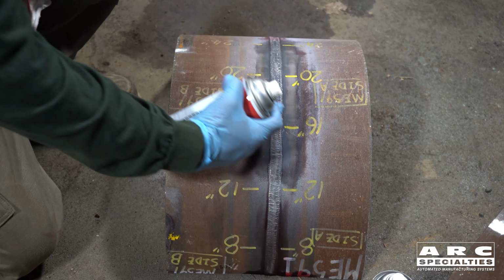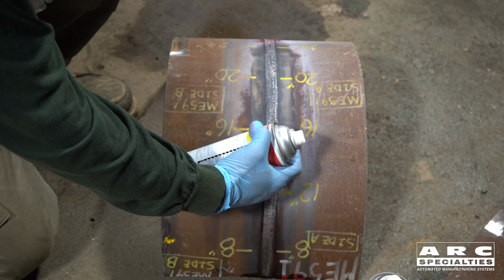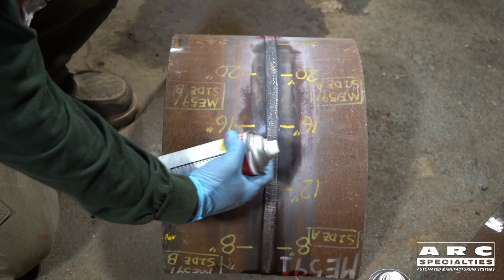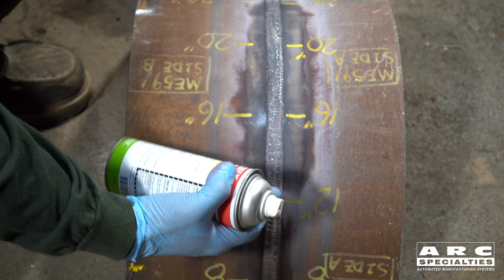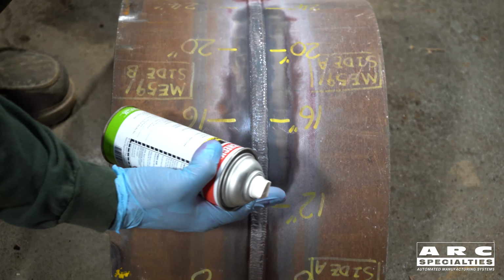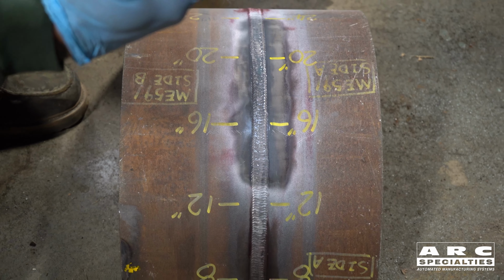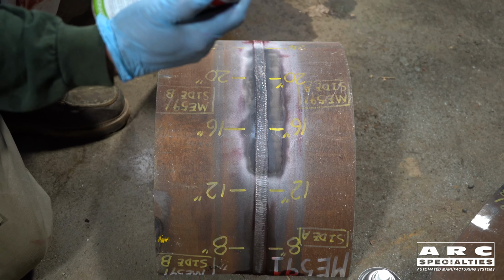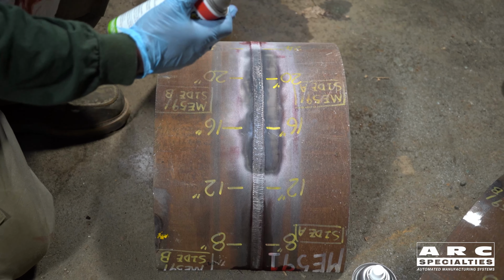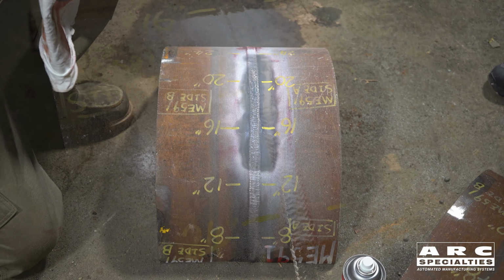We apply this, you want to go out 1 inch from the toe of the weld to the heat affected zone on both sides of the weld, cover the whole area that you have put penetrant on. And then we have another 10-minute dwell with the developer as well before we can make any calls on any indications that are shown in this weld.